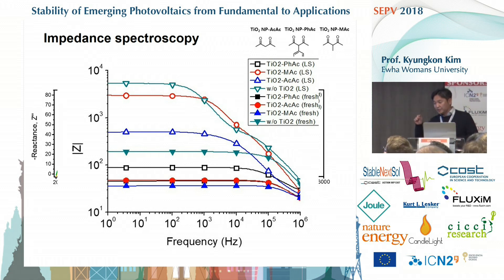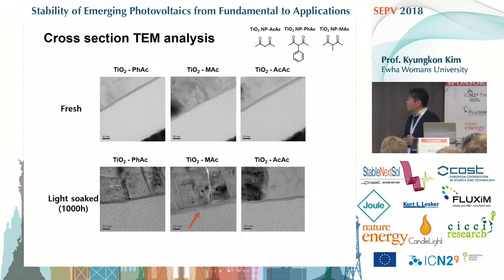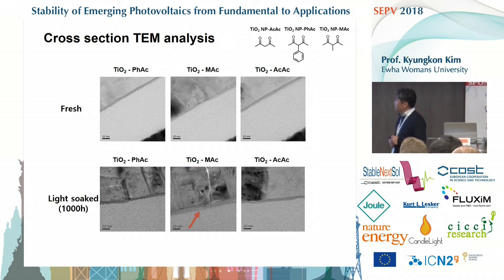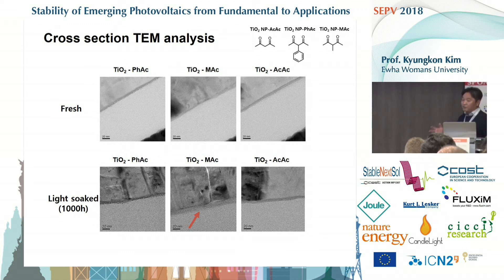We suspect that maybe the methyl-acac TiO₂ can be interdiffused into the active layer. We took a look at the TEM using cross-section TEM. As you can see, the phenyl-acac maintained the interface. However, in the case of TiO₂ with methyl-acac, there is interdiffusion of the methyl-acac into the active layer. That is why this device behavior is similar to the case without titanium dioxide.